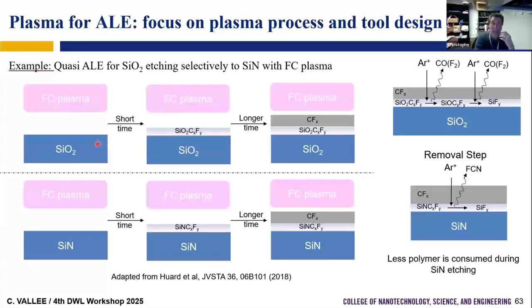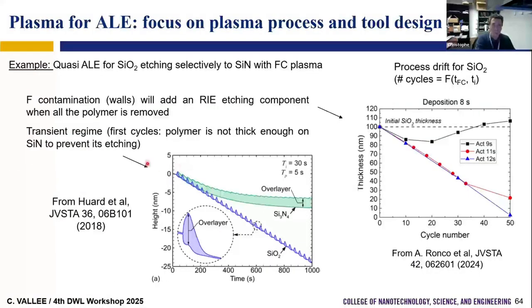So this is an example. If you want to selectively etch oxide versus nitride with this fast quasi-ALE process, you pulse the fluorocarbon. And we know that when we use a fluorocarbon chemistry, depending on the nature of the silicon substrate, whether it is silicon, silicon oxide, or silicon nitride, we will not develop the same thickness of polymer. For example, the thickness of polymer on nitride would be higher than on oxide. So when we do the removal step, we can still etch silicon oxide. But if the thickness is too high on silicon nitride, you will not consume the polymer during the etching. And so you still have some remaining polymer, and you will not etch the silicon nitride. So you may have a quasi-ALE process etching silicon oxide selectively to silicon nitride.